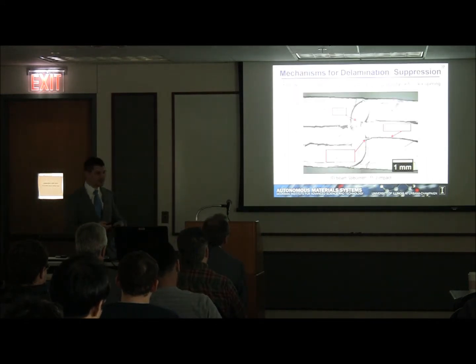Interestingly, and sort of expectedly, the 2D composites tend to exhibit more delamination opening and length as we increase impact energy compared to the 3D composites. And we believe there are two mechanisms which act to limit the delamination opening in the 3D composites. One of the mechanisms is depicted in this image.